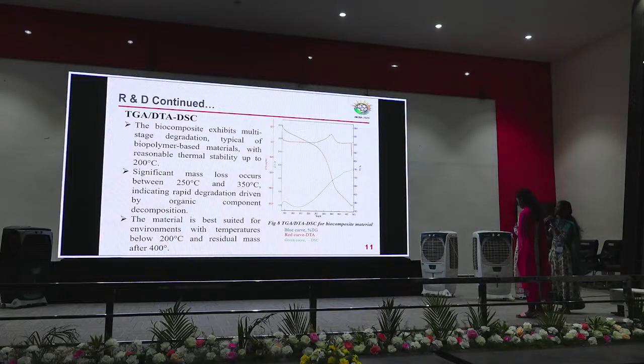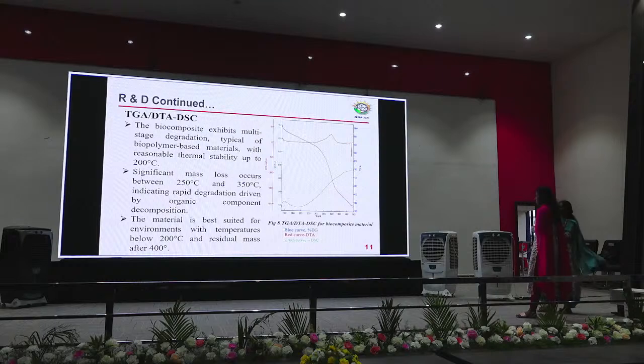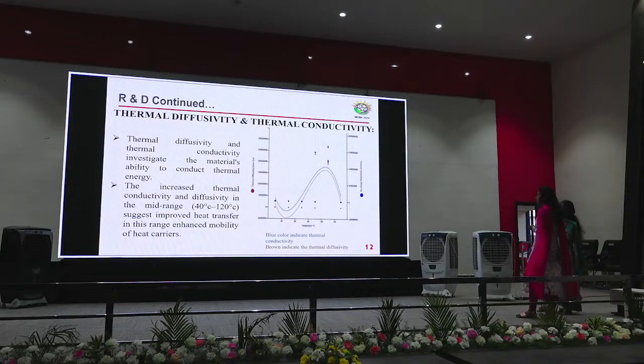DSC is represented by the green curve. It shows whether the process is endothermic or exothermic. In our material, it shows an endothermic process, which means thermal energy absorption. Thermal diffusivity and conductivity are used to analyze the ability to conduct thermal energy. Both curves show similar ranges from 40 to 120 degrees Celsius, which shows optimal heat transfer. Later it is reduced.